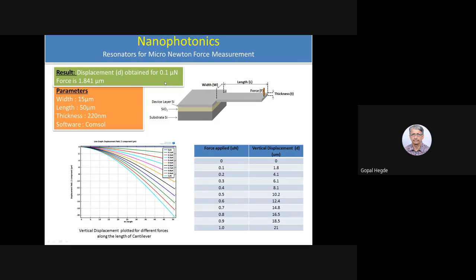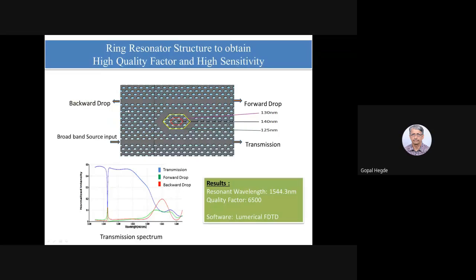Then we proposed a device. This is a cantilever, and we use a nanophotonics device, that means we use light for the measurement. We modeled that one. This is the standard way of fabricating the cantilever. We introduced a photonic crystal structure, a photonic crystal hexagonal ring resonator structure to display high quality factor and high sensitivity. So we introduced this nanophotonics device at the neck of the cantilever.